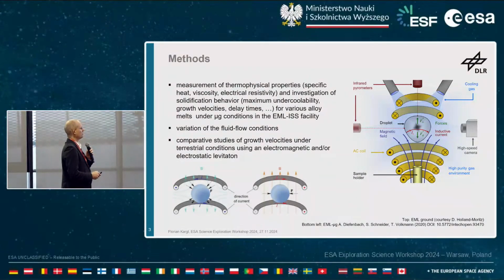If you go to microgravity, then the coil system looks a little bit different. So it looks much more simple. But you have a superposition of two fields. You have a quadrupole field that basically holds the sample in position against the small rest acceleration that you might have. And then on the other hand, you have a heating field that goes in one direction that induces again eddy currents, and you heat up the sample inductively. And this also leads to stirring.